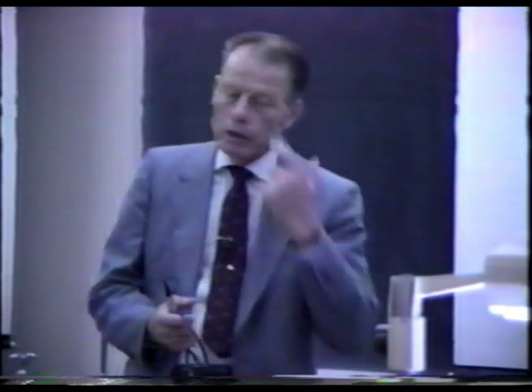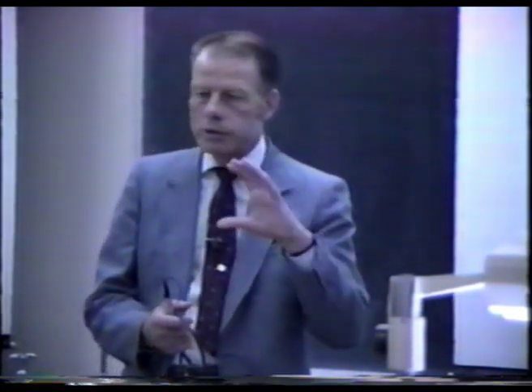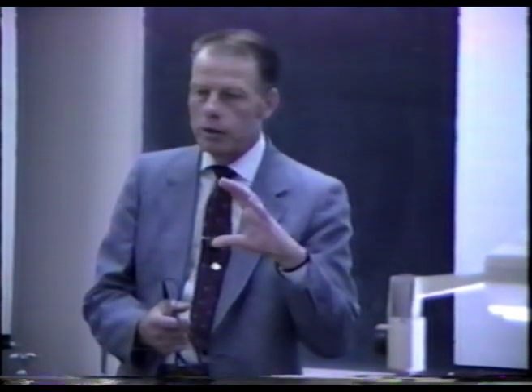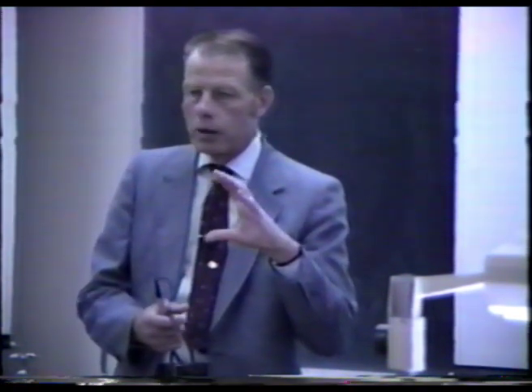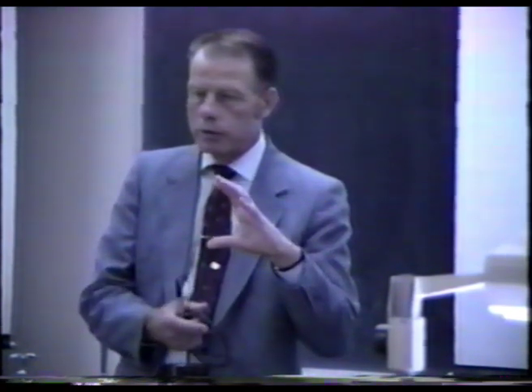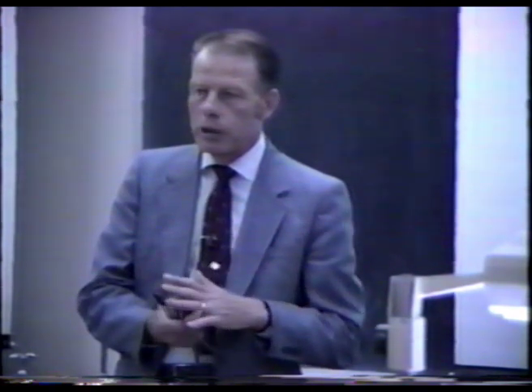Yeah, that can help, but that can also create problems as well. If you're, like we're doing, when the gases are coming out, you're really chewing up your electrolyte at a very fast rate. So mainly it's an equipment limitation for us right now. We would have to change our entire calorimetry, which is a certain size. Inside our calorimetric cell we only have 16 cubic centimeters of electrolyte, because to do good calorimetry you need a rather small volume when you're using these electrodes, so you can really pick up the heat quite readily. So we would have to completely scale up everything, and that would take money. That's the only problem.